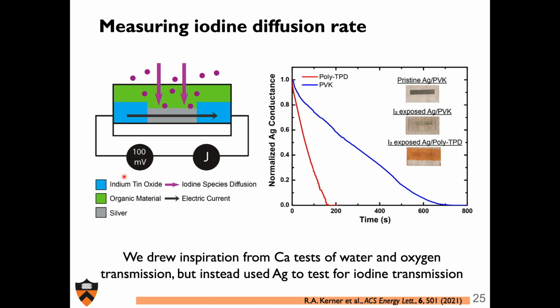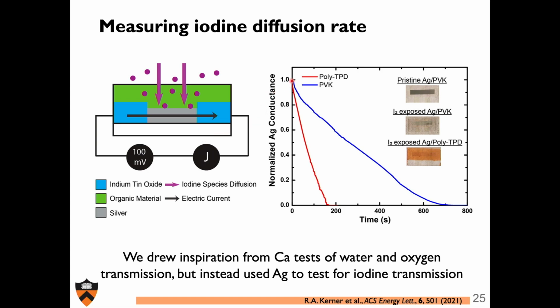We've measured iodine diffusion rates basically the same way that a calcium test works. Calcium is a good test for oxygen or humidity. You look at how much time it takes for calcium to be oxidized and rendered insulating in the presence of oxygen or water, and we've just ported it over to iodine. Silver is a good one, because it doesn't care about the presence of oxygen and water, but iodine will quickly render it insulating. So we can measure the amount of time it takes, upon exposure to an iodine ambient, for that silver to be decommissioned, to be rendered insulating and non-conductive.